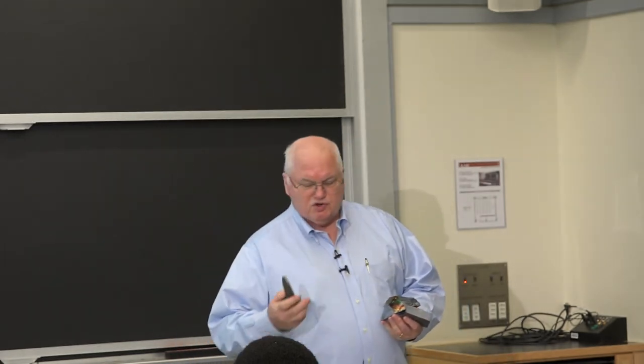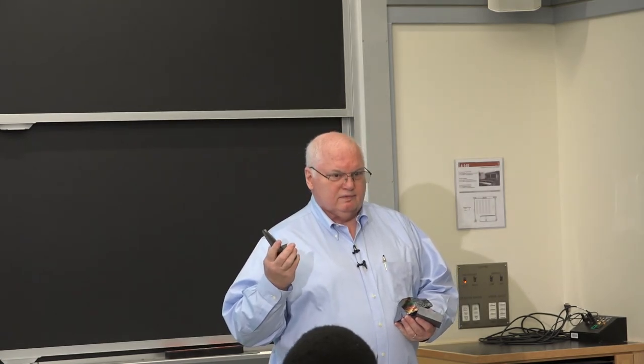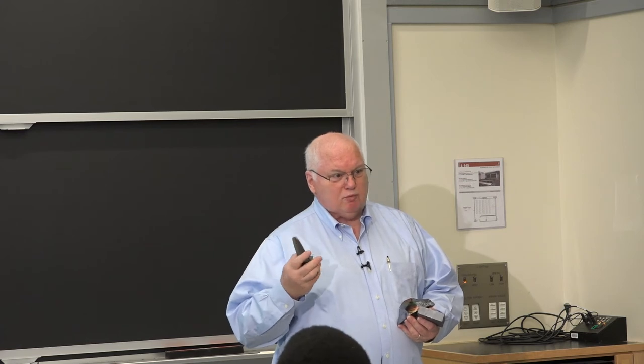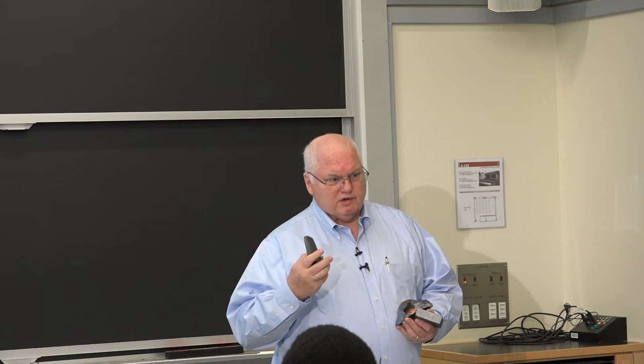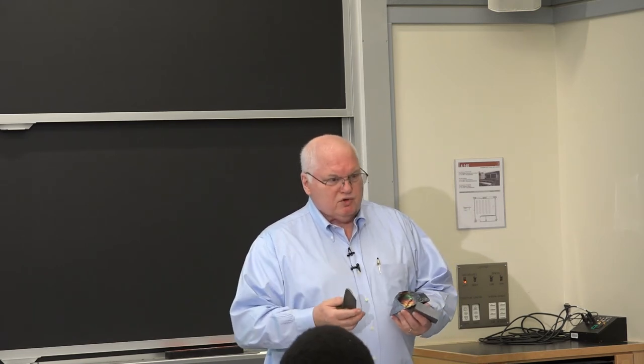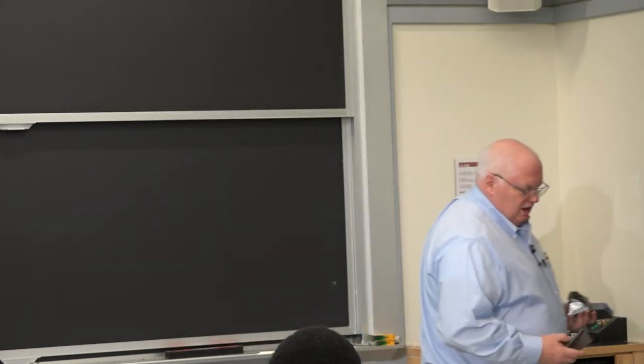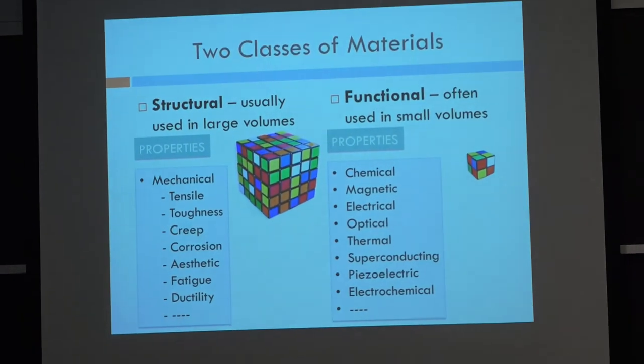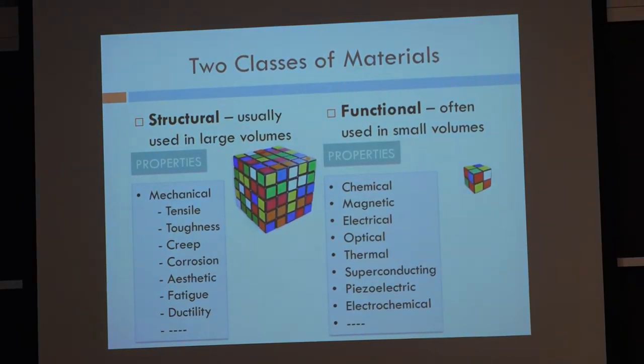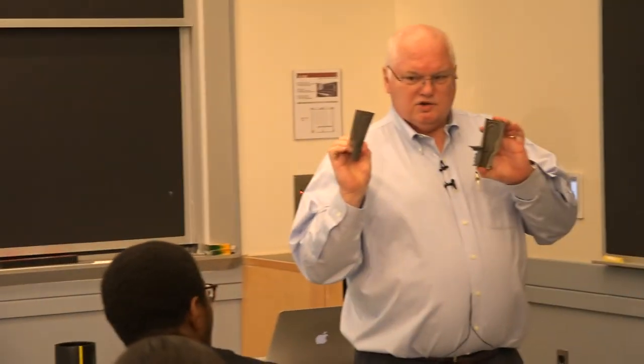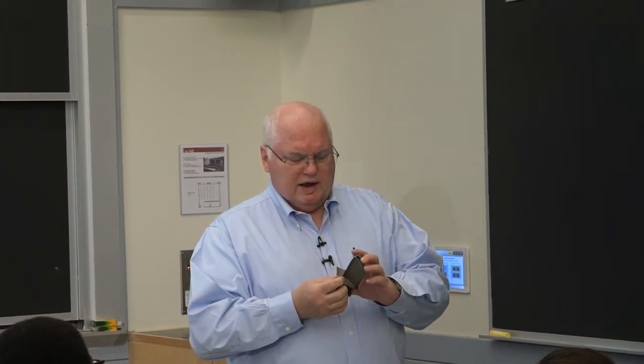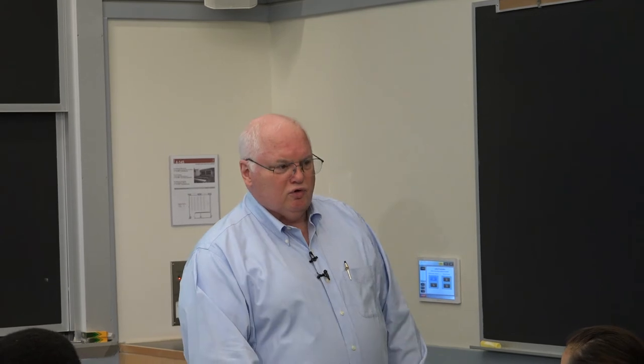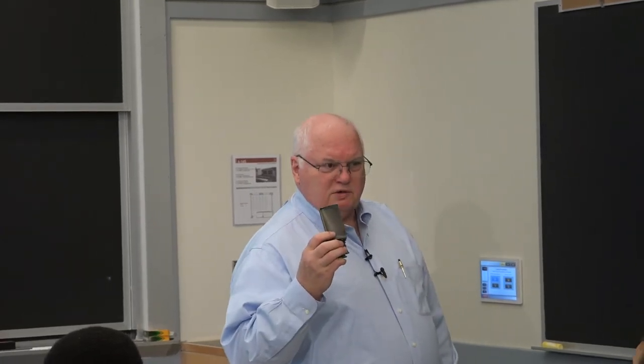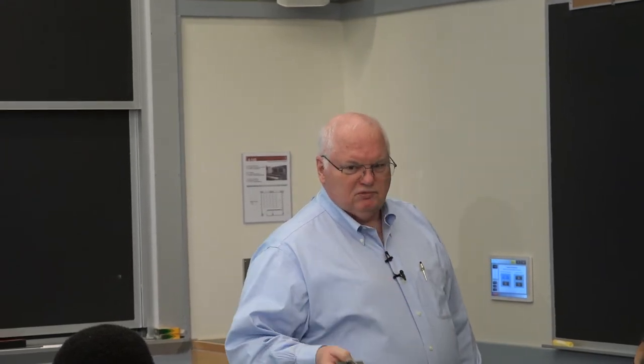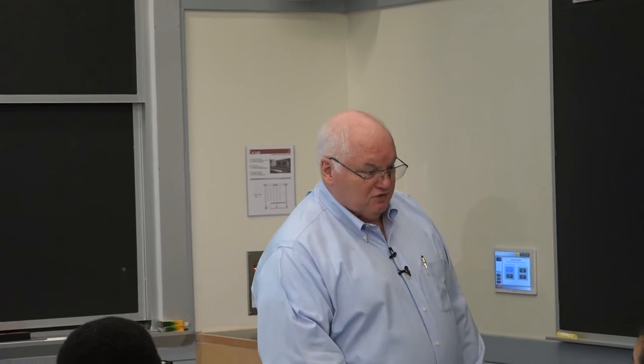We have some single crystals that are structural materials. This is a turbine blade. And this is actually a single crystal because we need the mechanical properties, we don't want the grain boundaries. Actually, we don't want the grain boundaries in any of these, but we go to large grains to get away from the fine grain size, okay? This particular single crystal has been cut in two. When they solidify it at 2,400 degrees Fahrenheit, they actually create these internal cooling passages, and then they laser or electron beam drill holes in here for cooling channels. Each one of these is worth about $4,000 a piece, and every disc on a turbine has close to 100. So if you want to know why the engine costs $5 or $10 million, you've got $1 million in one disc with the blades, okay?